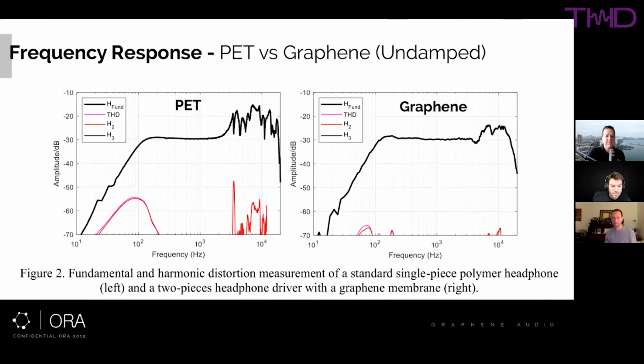That's awesome. Is this response a free field measurement, or is it built into a headphone? So this is in an IEC baffle without the damping paper on the back. In order to get the bass response, we basically remove all the acoustic damping and then measure it in a baffle.